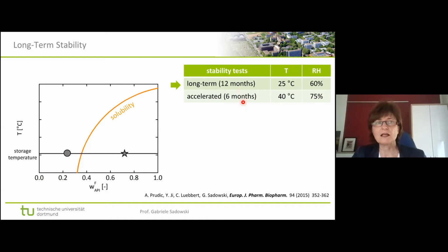But this is the idea behind it: before you give a medicine to a patient, you make sure that it's stable when stored at home conditions. And of course, if you have water in the atmosphere, then it will be absorbed in the ASD, because the API on the right-hand side is very hydrophobic, but the polymer usually is not. If you take a tablet, it should dissolve. So the polymer is usually chosen as a hydrophilic one, so that it dissolves very fast, then releasing the API. That's the idea. The disadvantage is, if you have a hydrophilic polymer, it does not only dissolve very fast in water, but it also absorbs water from the atmosphere to a certain extent.